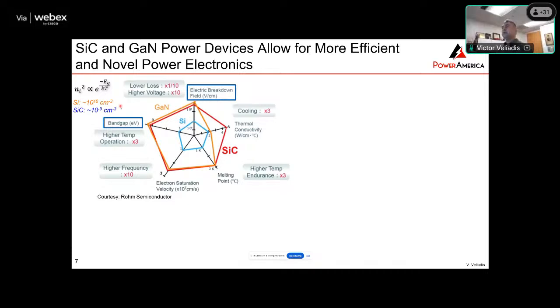So having a wide band gap means that at room temperature, you have very few excited carriers. In silicon, it's 10 to the 10th at room temperature. In silicon carbide, it's 10 to the minus 9th, so 19 orders of magnitude lower. So the fact that you have a wide band gap means that at room temperature, you have very few excited carriers. That means that your leakage is very low, and it also means you can operate at higher temperatures. So let's see what the wide band gap and the large electric breakdown field mean in terms of making devices.